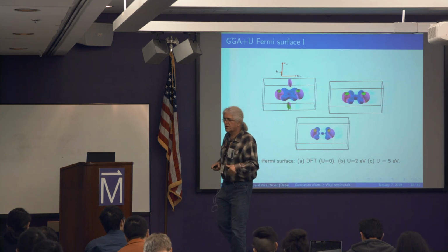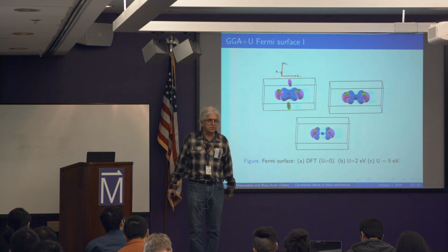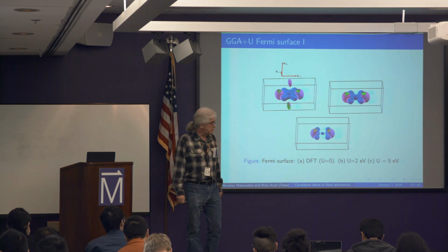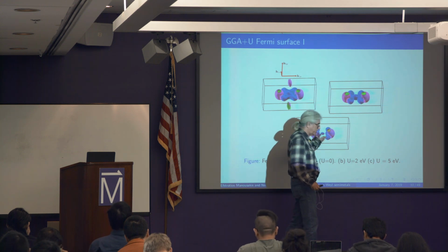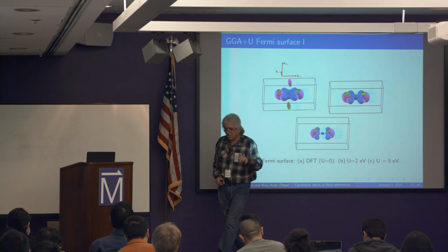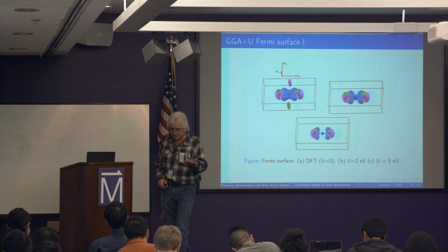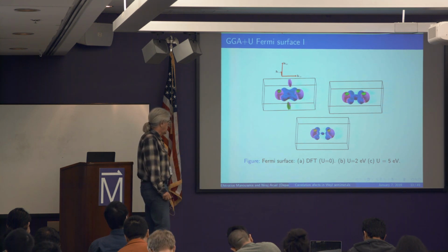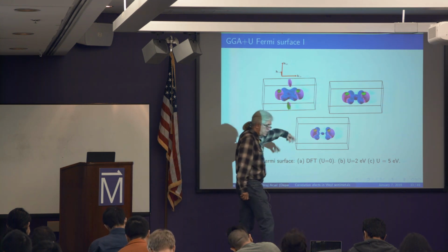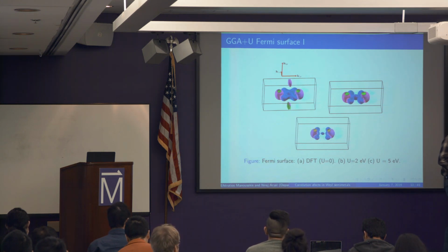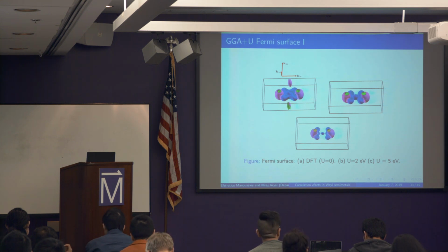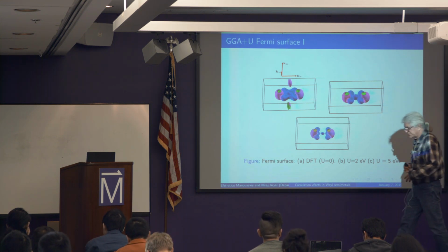But the point is that we are close to this Lifshitz transition either way. So quantum magnetoresistance might be huge because the magnetic field will fluctuate the Fermi level slightly. As a result, you're going to have big changes in the shape of the Fermi surface from just a small few Tesla magnetic field. So you will have a hugely different response.